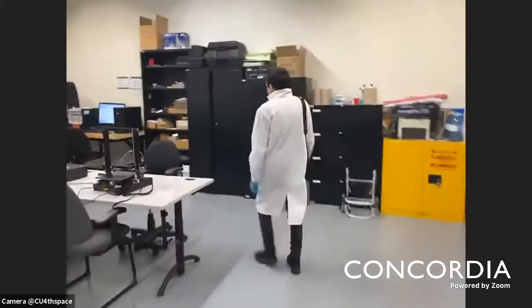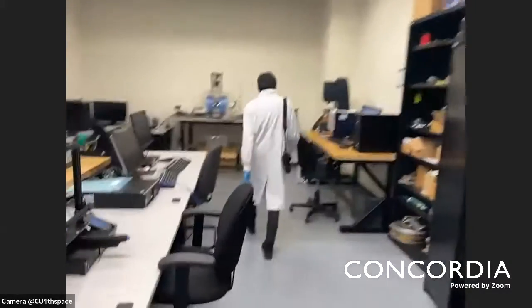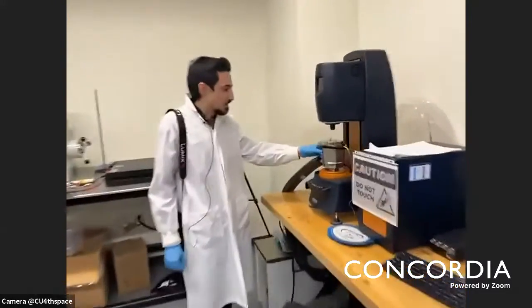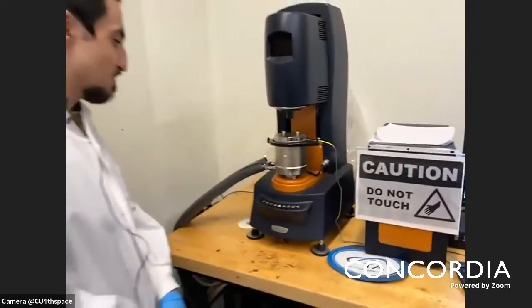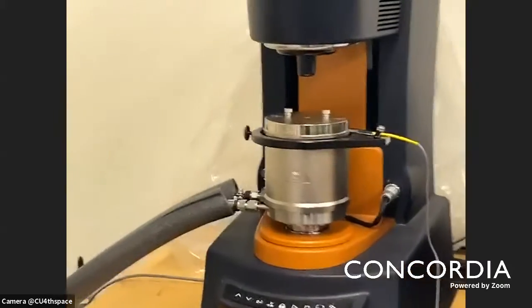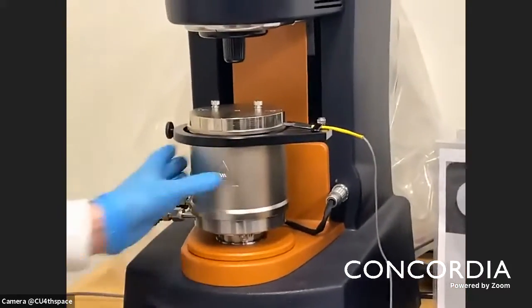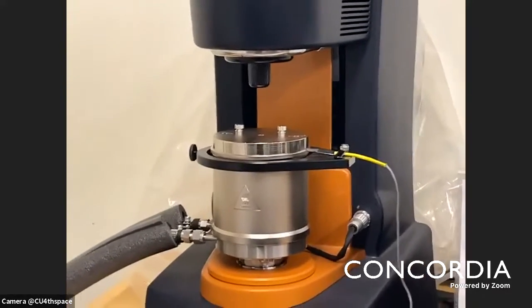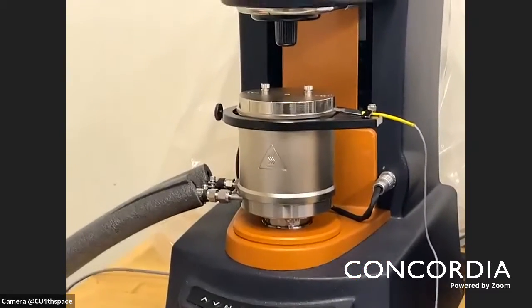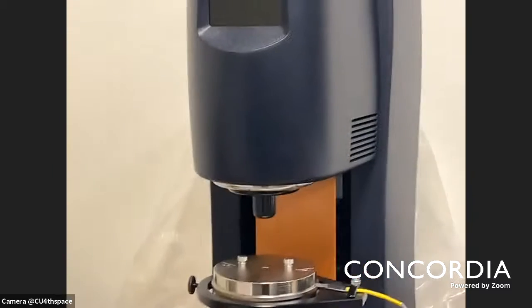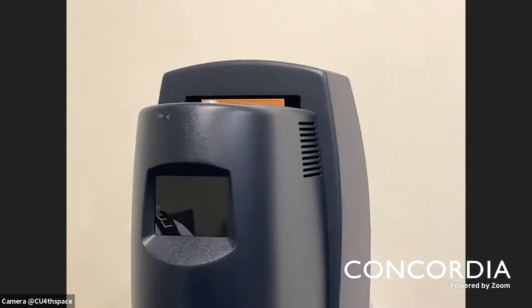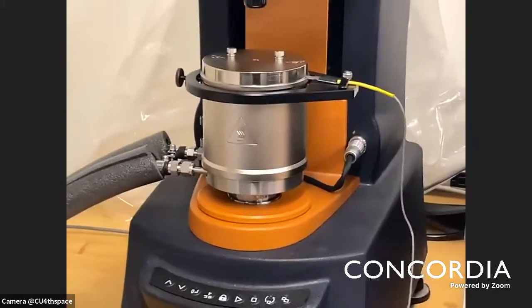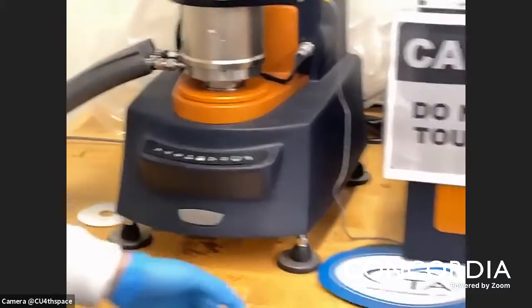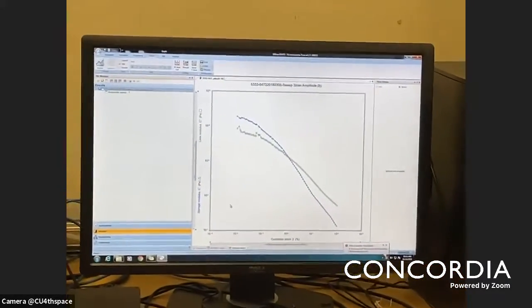So also here, we are using this kind of device to apply the field by using this electromagnet to see the response of the material. Also, this kind of rheometer has the advantage of changing temperature. You can change the temperature and see the difference in the response of the material, because the MRE is very heat sensitive. Also, as you see here, this is the result that we extracted from a sample.